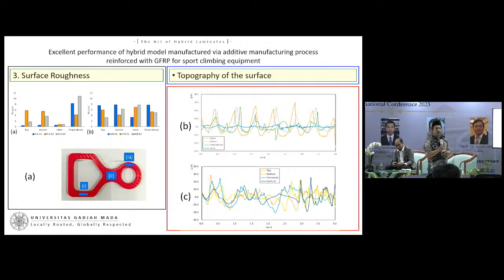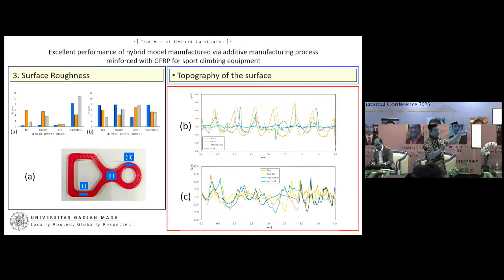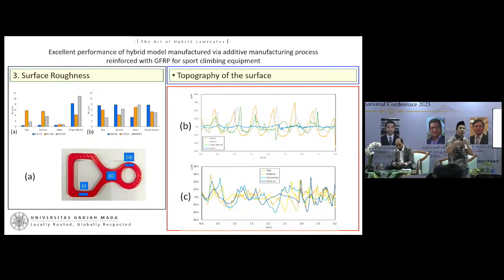How about the surface roughness? If you check the surface of our products in the 3D printer models, they usually have peaks and valleys, like in the B models, going up, down, and up, down. But when we use the hybrid laminates, the surface cannot be completely predicted. The surface more or less follows the glass fiber laminate itself. Compare B, which is pure PLA, and C, where we combine it, the hybrid laminates.